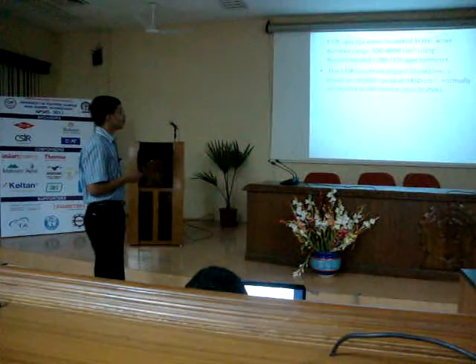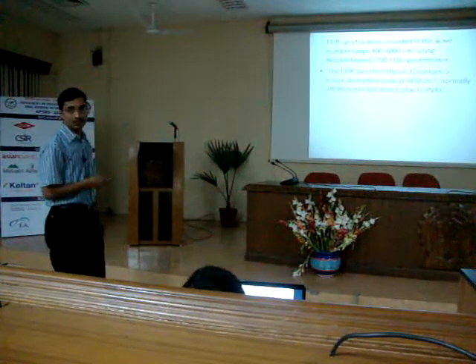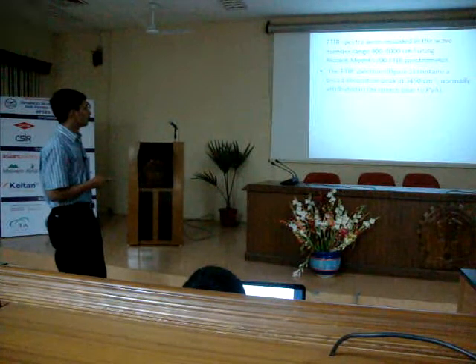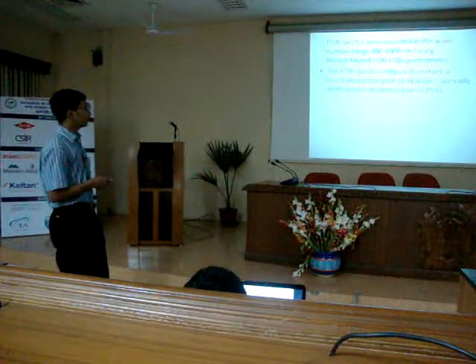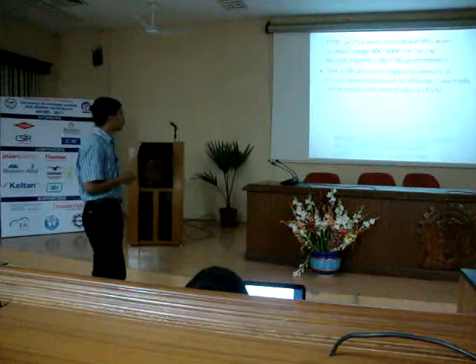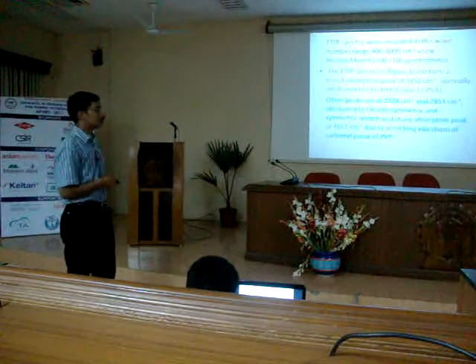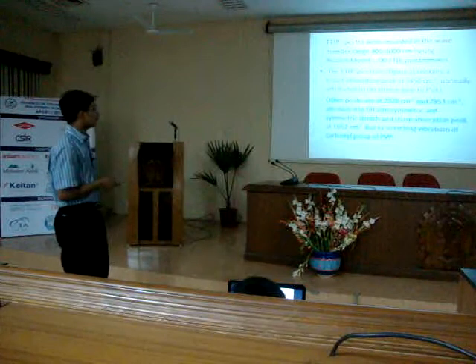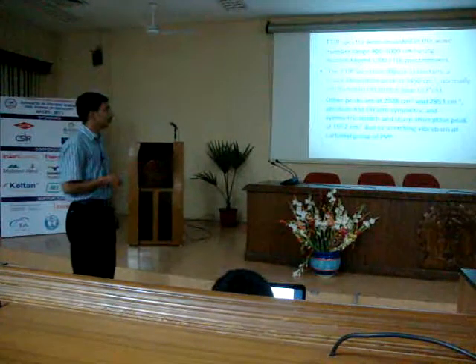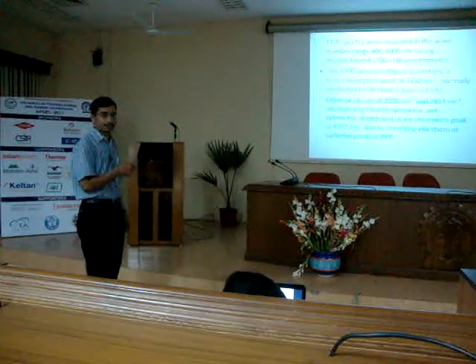Now FTIR spectra were recorded in the wave number range of 400 to 4000 per centimeter using a Nicolet model 5700 FTIR spectrometer. The FTIR spectrum contains a broad absorption peak at 3450 per centimeter, normally attributed to OH stretch due to PVA. Other peaks are at 2928 per centimeter and 2853 per centimeter attributed to CH antisymmetric and symmetric stretch, and a sharp absorption peak at 1652 per centimeter due to stretching vibrations of the carbonyl group of PVP. So in the curve we can see the peaks showing the presence of PVA and the presence of PVP.